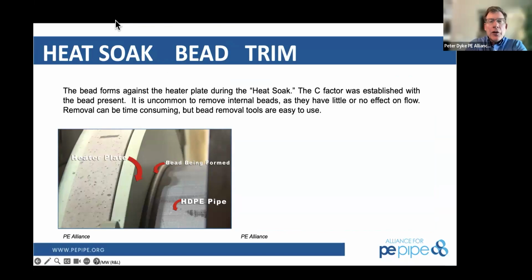Yeah, thank you for that. So during the heat soak, when we're preparing the pipe ends for fusion, we've got to heat them up so they can fuse. ASTM F2620 tells us we have to have a bead, and that bead size is an indicator of, are we ready to fuse or not?